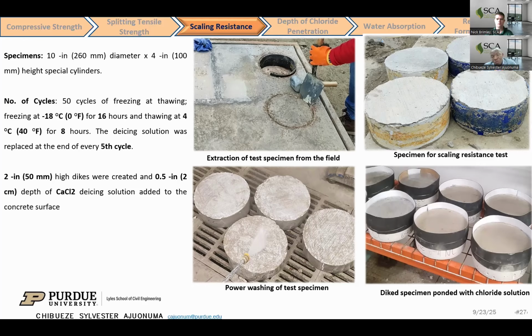They were exposed to 50 cycles of freezing and thawing. We had freezing at -18 degrees Celsius for 16 hours, and then thawing at 4 degrees for 8 hours. And the deicing solution was replaced after every fifth cycle, and this was repeated for 50 cycles.